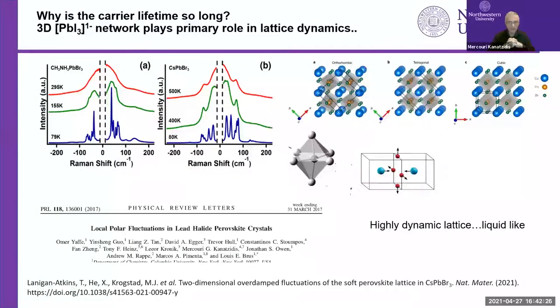dynamic. And this is, I think, the origin of why the carrier lifetime is so long and why it's defect tolerant. Basically, what you see here is the Raman spectra of this material at low frequencies. And this is compared with methylammonium, another analog, an organic-inorganic material, similar. And basically, this red spectrum is very broad. It looks like the Raman spectrum of a liquid, suggesting that even though this is a crystal, the crystalline lattice is so dynamic, things are rotating and moving around to give this liquid-like response.